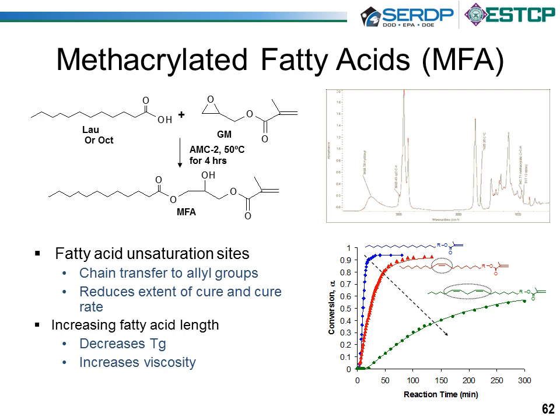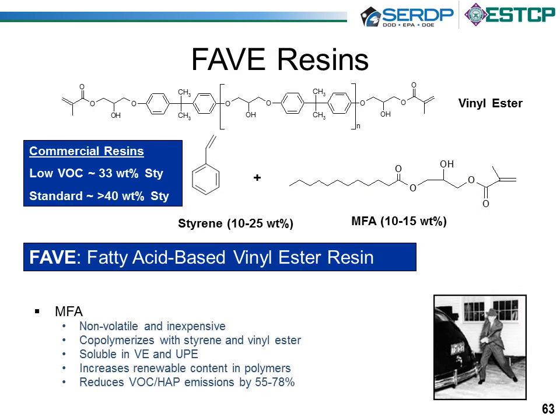And on the next slide, I show these fatty acid vinyl ester resins, or FAVE, that we made, which is a combination of vinyl ester cross-linker monomer, which is that top molecular structure there. And typically in commercial vinyl ester, that's blended with styrene, which is a reactive diluent used to reduce the viscosity of the vinyl ester. That vinyl ester molecule on its own, you wouldn't even know it's a liquid. It's a very, very viscous liquid. So it needs the styrene to do liquid molding applications. And typically we're talking about adding well over 40 weight percent styrene to the resin.